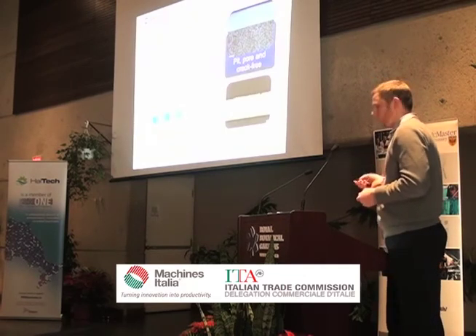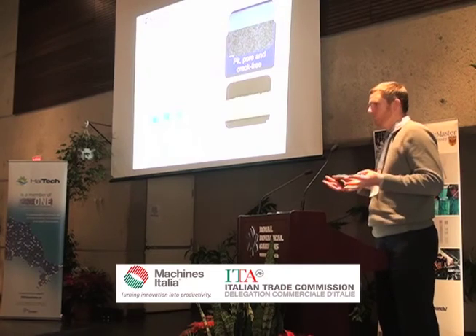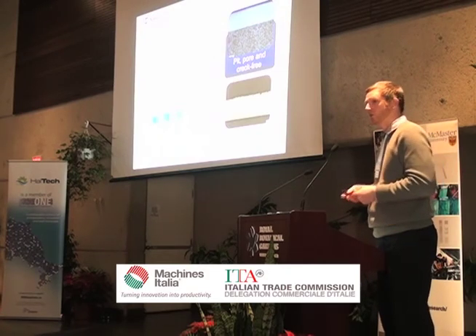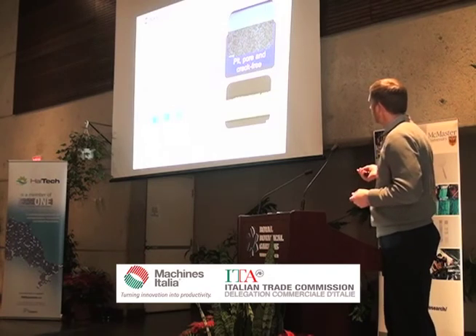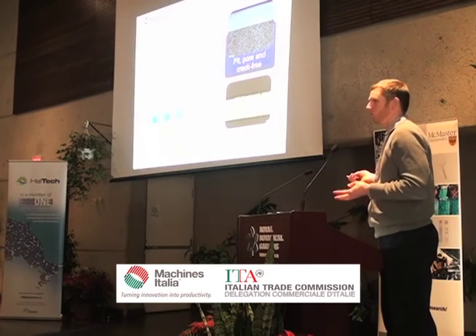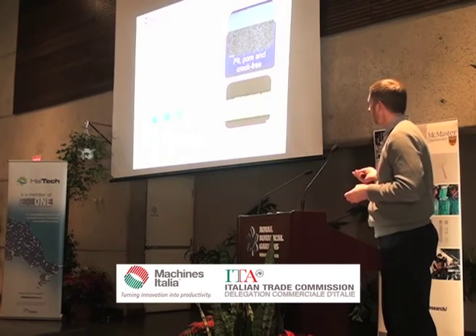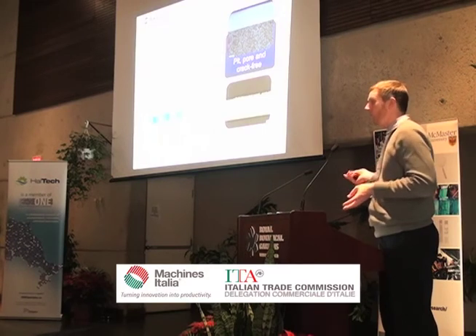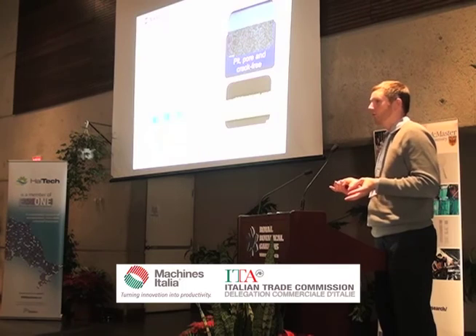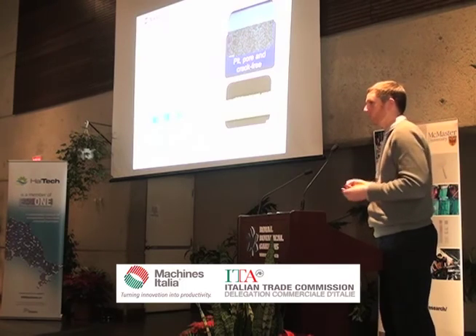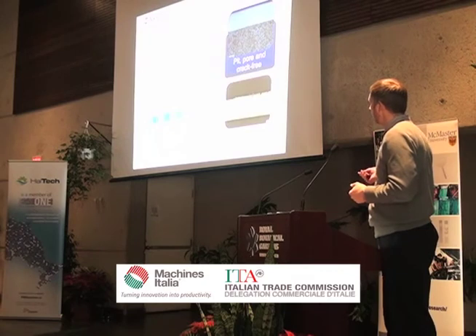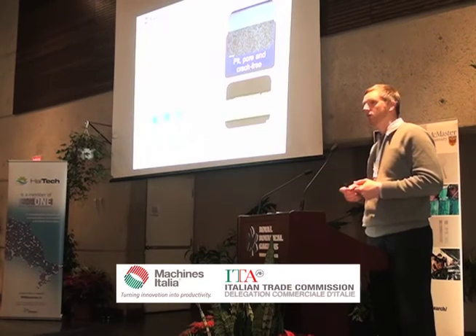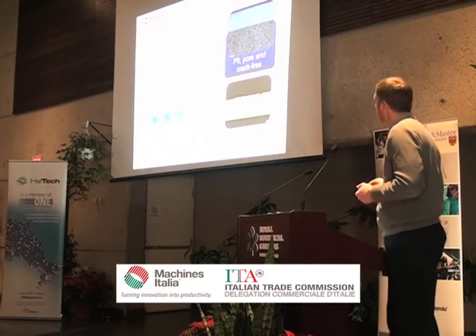Right, in terms of corrosion protection, when comparing us to hard chrome, salt fog corrosion resistance is always of importance. So what we're able to show is that there's a very significant difference between what hard chrome is and what our material is. Hard chrome, by nature, is microcracked. So this is a cross-section of your typical hard chrome plating. In a lot of ways, it actually makes it perform better. But in terms of sliding wear and the kinds of salt spray that we're requiring here, you can get integranular corrosion and some material coming off. Ours, our Nanovate CR, on the other hand, is pit-free and crack-free, so it makes a very smooth and hard surface to be maintained.